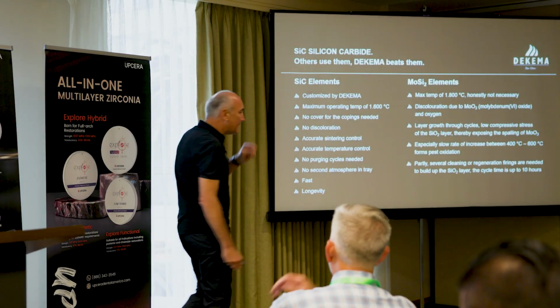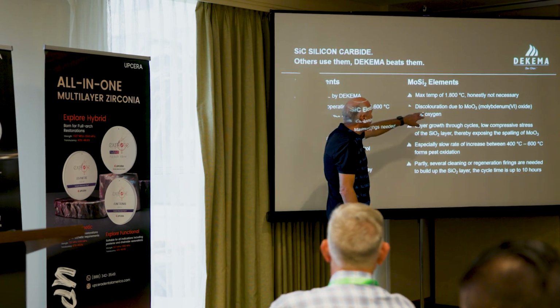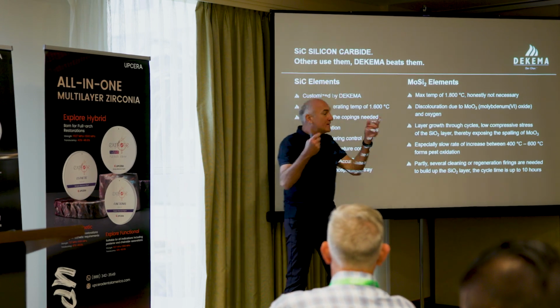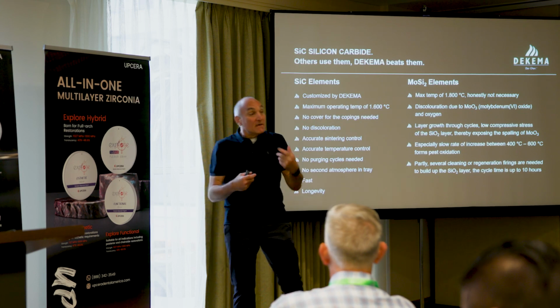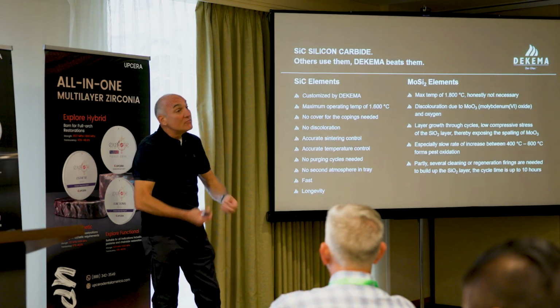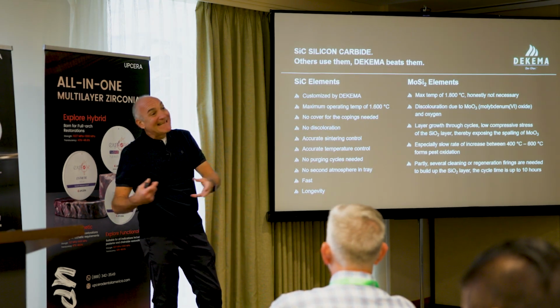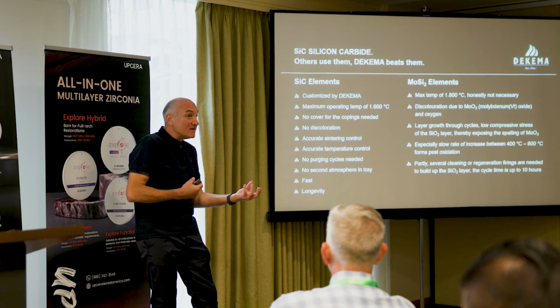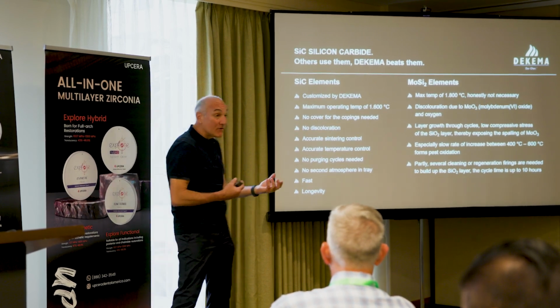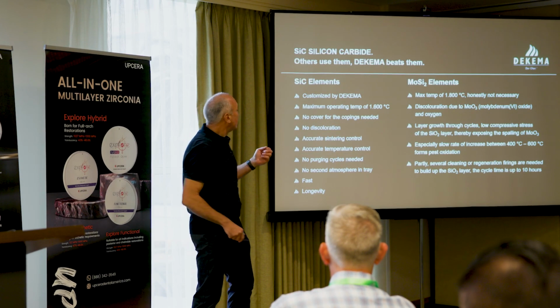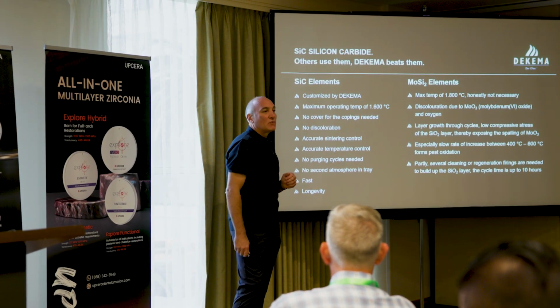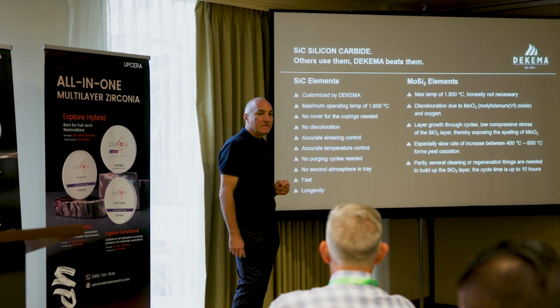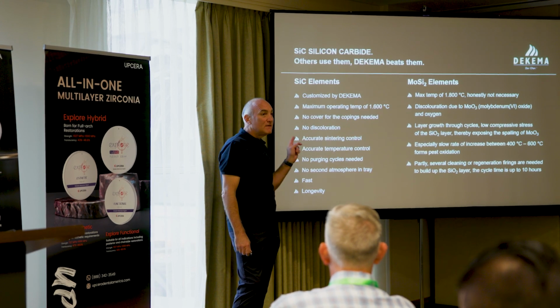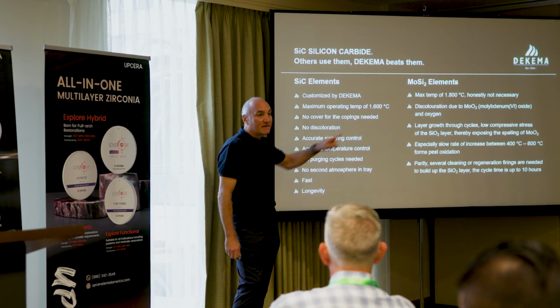There's a small difference, and you can imagine from my explanation before that these heating elements build up these glass layers. So surely the longer you reduce it, the less you have a good result, because there's no glass layer anymore. But still, we should talk about cycles, and then you will see that we talk about completely different longevity with a SiC element and with a MoSi2.